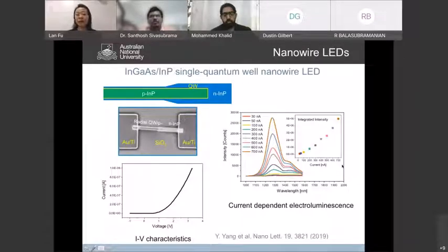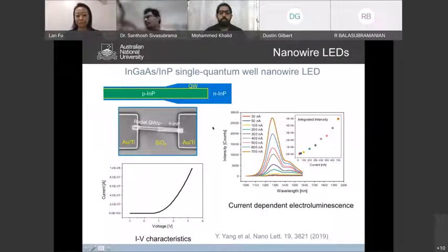Nevertheless, we said, okay, let's just put in some dopant, making it into an LED structure, and see if we can make an LED. And then, as you can see from here, we actually made a single nanowire LED by just contacting the n-doped indium phosphide shell and then doing some etching to expose this p-type doped indium phosphide core, and we're actually making an LED. We inject current. You can see the electroluminescence coming from this structure, showing we have a very nice LED, light emitting at 1.3 micron from this quantum well structure.